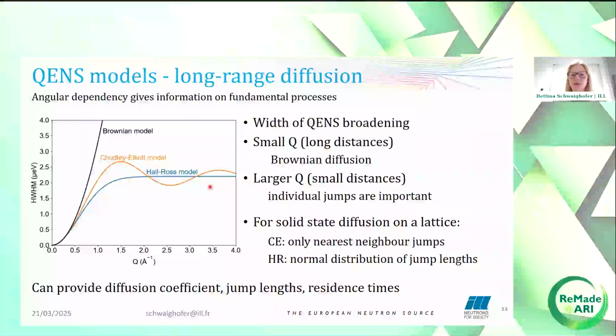For solid-state diffusion on a lattice, there are several models, two of which are the Chudley-Elliott model and the Hall-Ross model. The Chudley-Elliott model describes only nearest-neighbor jumps on a lattice, whereas the Hall-Ross model includes a normal distribution of jump lengths. And as you can see, the behavior of the half-width at half maximum at large Q differs between the models. Therefore, by fitting these models to our data, we can extract diffusion coefficients, jump lengths, and residence times of the diffusing atoms, as well as get an idea of the diffusion pathway.